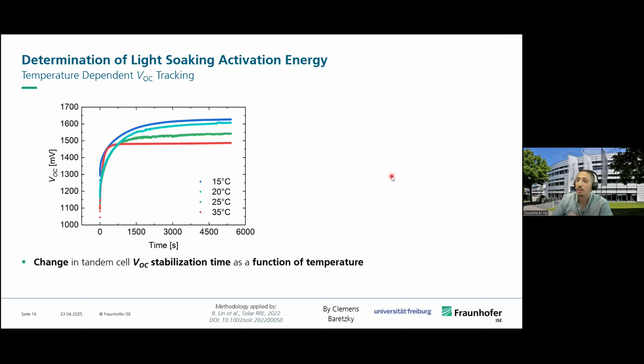We also measured temperature-dependent VOC. In this experiment, we had the cell on a chuck where the chuck's temperature was varied from 15 degrees to 35 degrees. And at each temperature, we saw how the VOC changed with time. So here you can see that it's really a temperature-dependent process, and that the higher the temperature, the faster the stabilization time of the VOC. So heat can also activate this light soaking phenomenon.